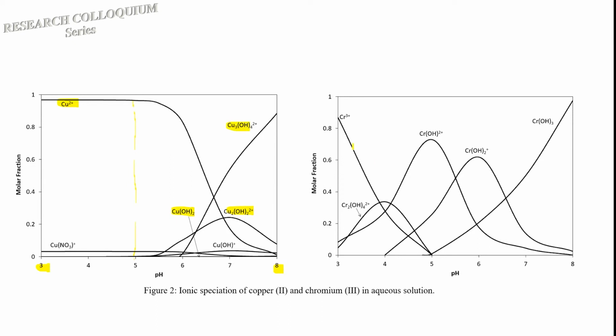On the other hand, if we look onto this chromium, the graph is extremely messy. From pH 3 until pH 5, you may realize that at this pH 5, most of the Cr3+ is already converted into the chromium hydroxide complexes. Bear in mind that these all hydroxide complexes, they have reduced valence charge, and also the hydrated radius could be larger. So when we thought that larger hydrated radius and also lesser valence charge means that the diffusivity of this chromium is reduced already. Eventually, the copper 2+ will gain advantages over this Cr3+ because Cu2+ is still remain as Cu2+, and hence the diffusivity will be much more higher if compared to the chromium hydroxide complex.